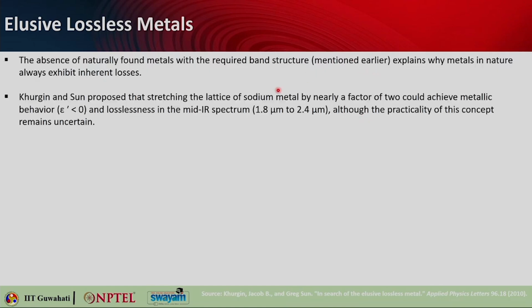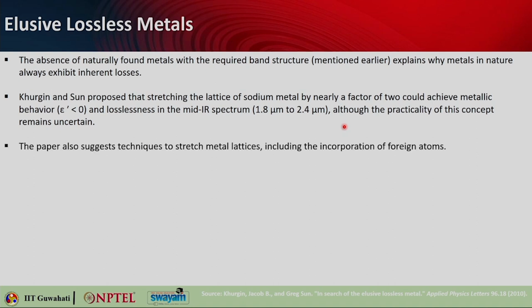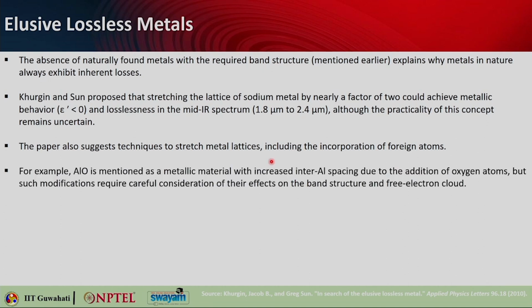So, Khurgin and Sun, in this particular paper, proposed that stretching the lattice of a sodium metal by nearly a factor of 2 could achieve metallic behavior, that is the real part of permittivity being negative, and lossless in a particular spectrum, that is in the mid-IR, 1.8 micron to 2.4 micron. Although the practicability of this concept remains uncertain. So, they have proposed it, but they could not show it. The paper also suggests techniques to stretch metal lattices by including foreign atoms.